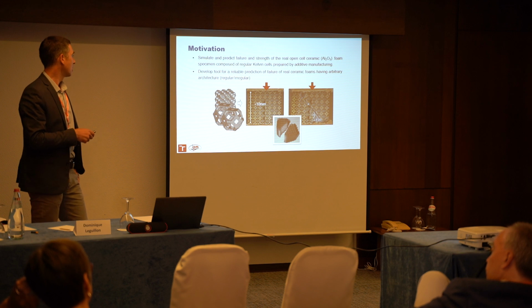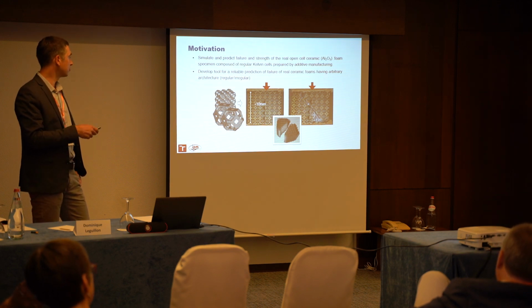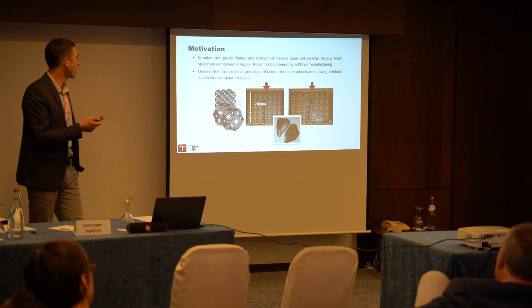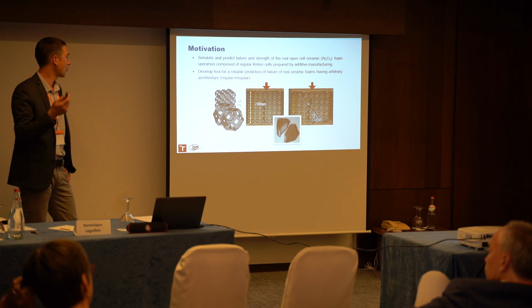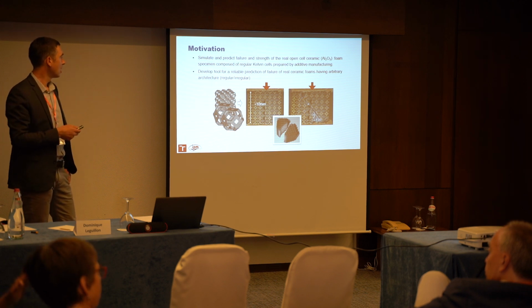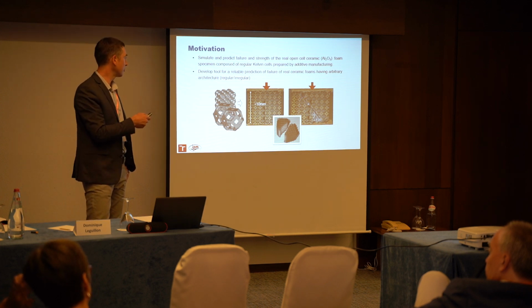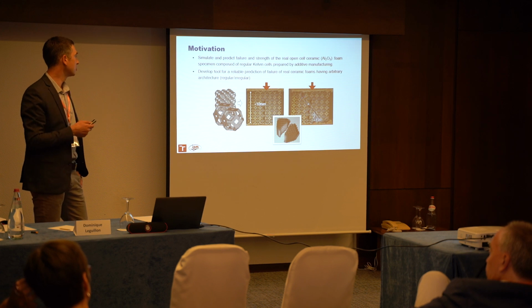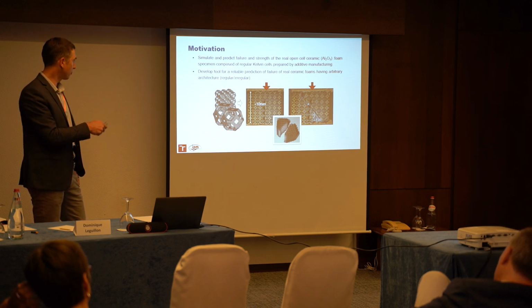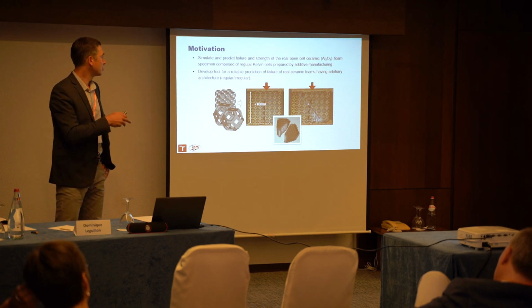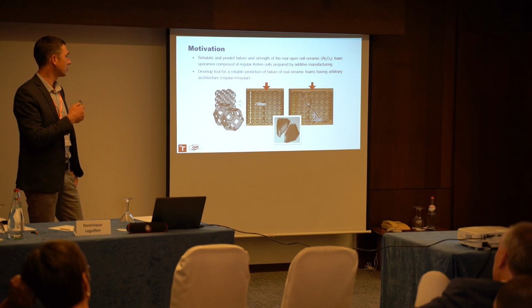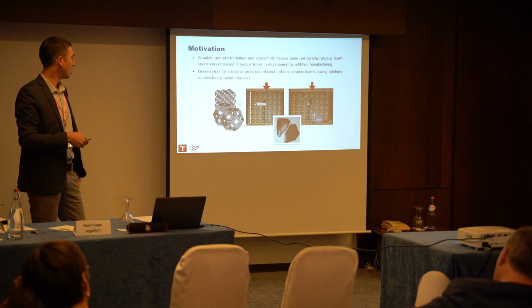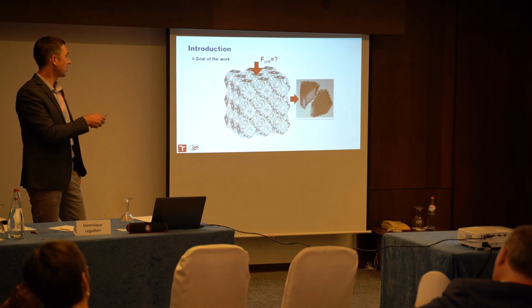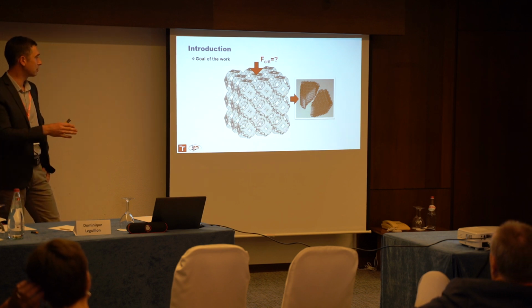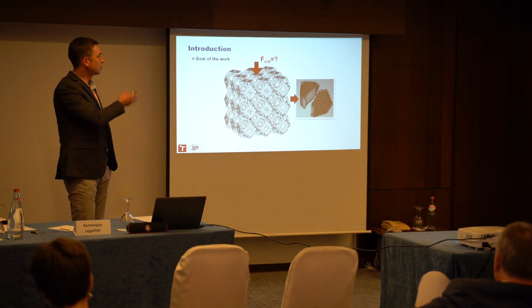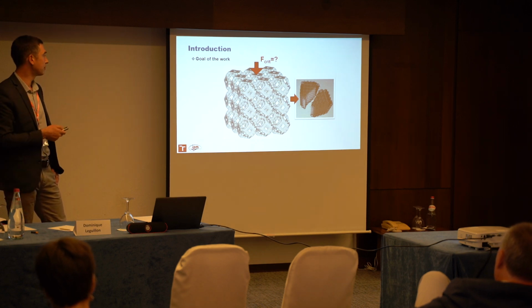So the motivation was to predict the fail force or strength of such porous ceramic structure. In this case, we produced ceramic foam using 3D printing technology from alumina material. This foam was composed of Kelvin cells, and we tested the compression, and we tried to predict the strength of such foam using the coupled criterion. So the aim was to predict both the critical force necessary to break the specimen, and also try to see if we can predict also the fracture surface. Okay, so